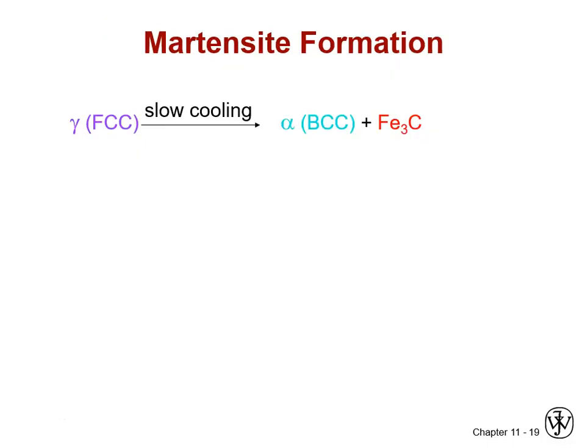Okay, so a little flow chart of martensite formation. If we slow cool, we don't get it. We'll just get our alpha, ferrite, and cementite either in a pearlite structure or hypoeutectoid and pearlite, or the very fine analog to pearlite, bainite, which is still ferrite and cementite. If we quench really fast and we don't give that carbon time to diffuse at all, we will go through our diffusionless shear transformation, and we will get our body-centered tetragonal metastable structure, which we call martensite, so hence the M.